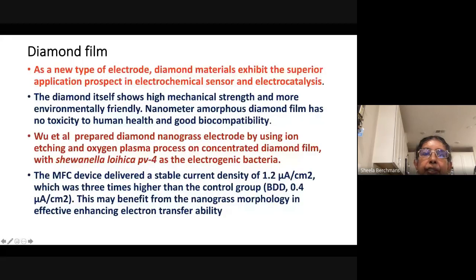So one of the reports, they have prepared diamond nanoglass electrode by using ion etching and oxygen plasma process on concentrated diamond film with the microorganism Shewanella loihica as the electrogenic bacteria. The MFC delivered a stable current density of 1.2 microamperes per centimeter square, which was 3 times higher than the control group. So this may benefit from the nanograss morphology in effective enhancing of the electron transfer ability.